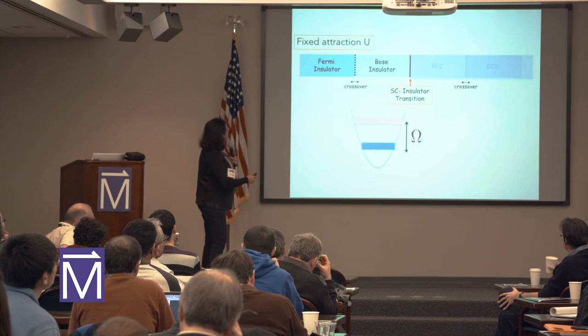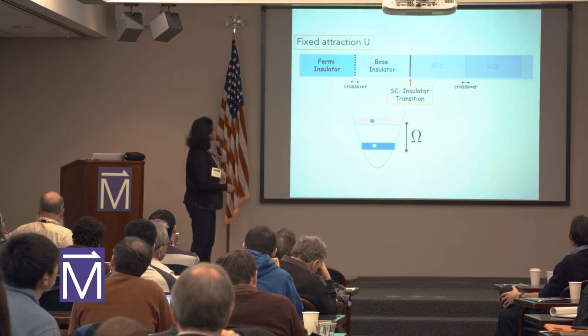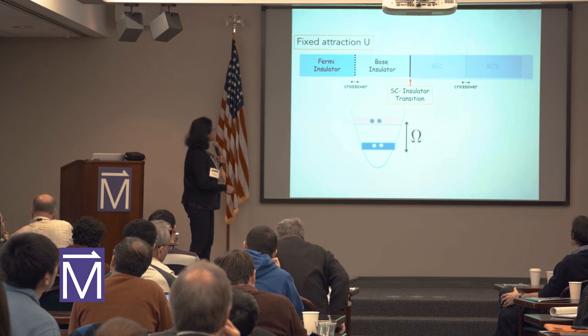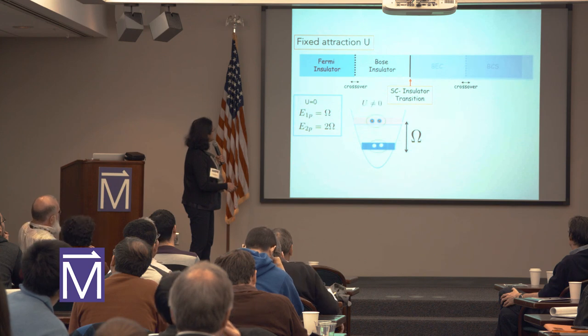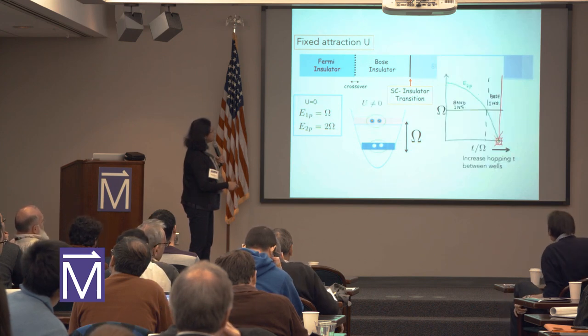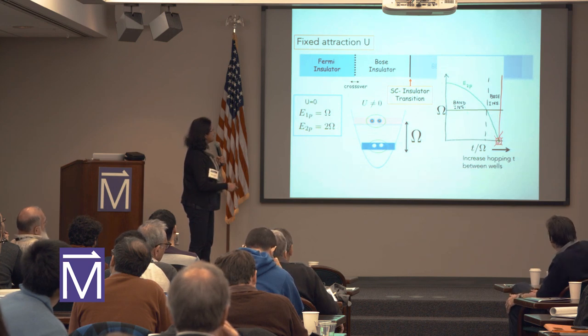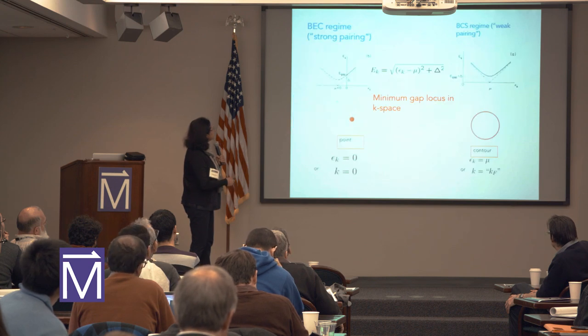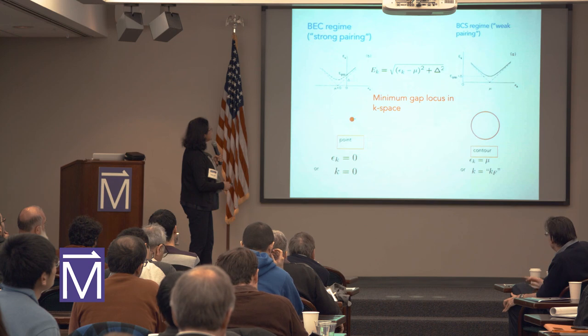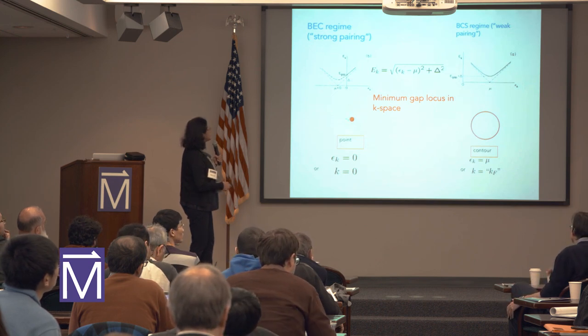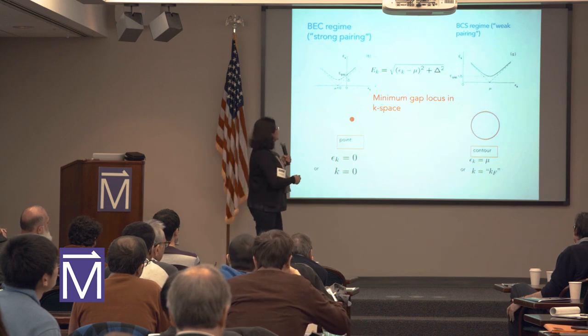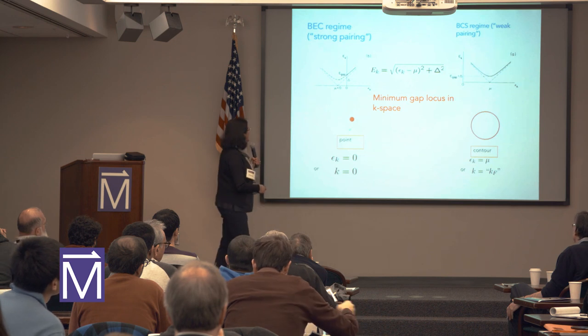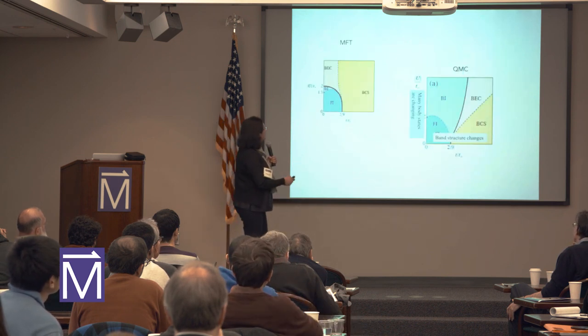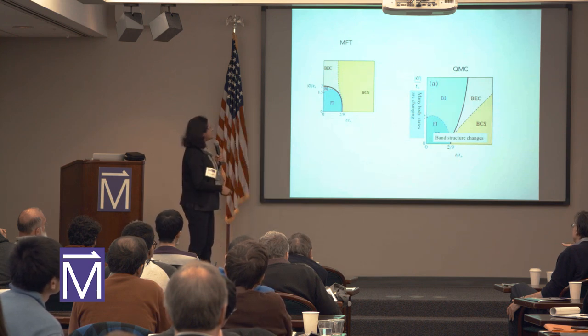When you include attraction now, you fix the attraction, once again change the tunneling, you see that you can create these two excitations in the band insulator, and the binding energy can actually drop below the single particle excitation. And that's when it becomes a Bose insulator. And this Bose insulator then undergoes BEC, which is essentially condensation at momentum equal to zero, and that minimum gap locus then undergoes a topological change from a single point to a whole Fermi surface. Okay, so I won't tell you too much more, but essentially you get a whole phase diagram in the space of attraction and tunneling, and it embodies all of these four phases.